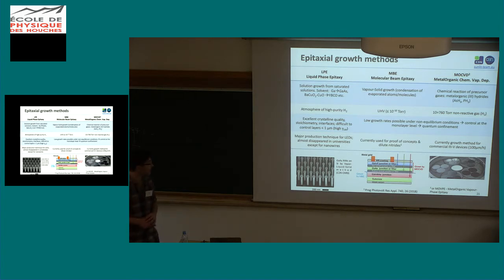The other main techniques are molecular beam epitaxy and metal-organic chemical vapor deposition, otherwise called MOVPE. In this case, it's a vapor-solid technique. You're essentially evaporating atoms in vacuum, and they will condense on your substrate, atom by atom. The condition to do this epitaxial growth is that you really need to have a very high, ultra high vacuum in the range of 10 to the minus 10 torr.